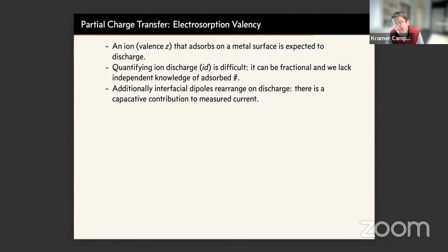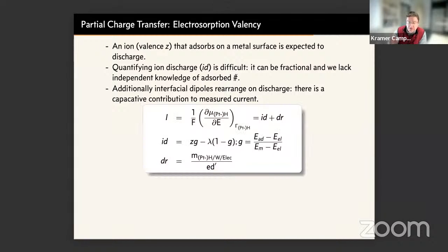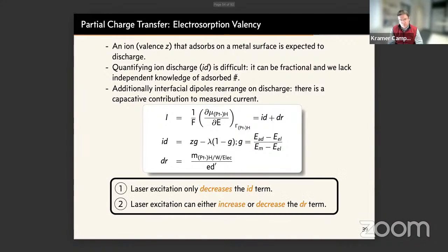So there should be a capacitive contribution to this measured current as well. So you can write some math. This, in fact, comes from a paper from Schmickler and co-workers. You can describe this as a change in chemical potential of the hydrogen, of this platinum hydrogen complex, and from an ion discharge component, this ID component, and from a dipole reorientation component. And the important point here is that this laser excitation offers a kind of unique ability to address this kind of discharge, right?